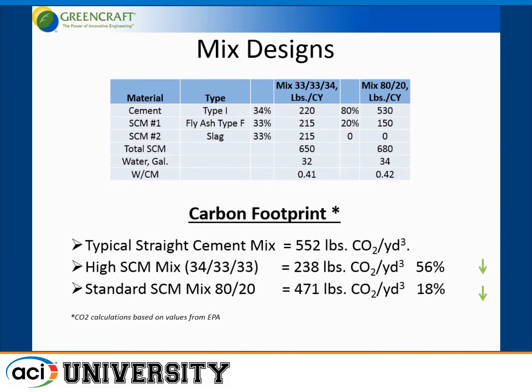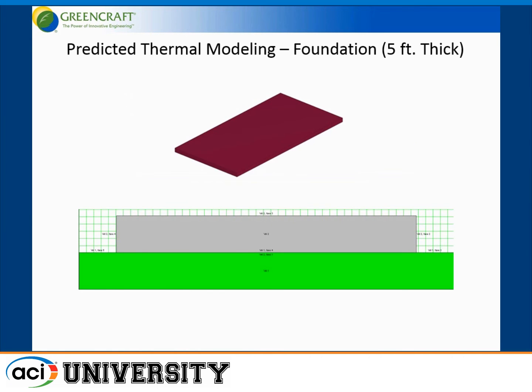We've taken the same two mix designs that we looked at before, and you can see here that a typical straight Portland cement concrete mix design has about 552 pounds of CO2 per yard. If you were to use the 1/3, 1/3, 1/3 mix, you have a 56% CO2 reduction, while the 80-20 mix, we have an 18% reduction. So here's our 5-foot thick mat foundation.